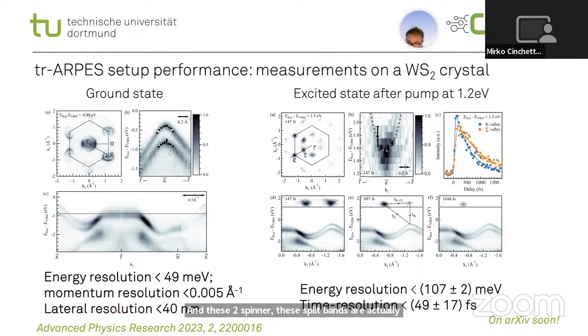Energy resolution and momentum resolution are given here. Now, if we do a time-resolved ARPES experiment, so now we also excite the system, for example, with a photon at 1.2 electron volt. So now we not only see the occupied bands below the valence band maximum, as you can see here, but we also see photoemission intensity in the conduction band.